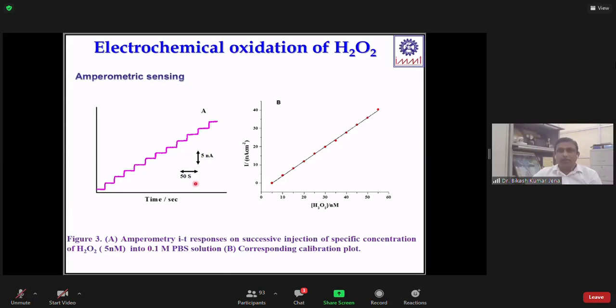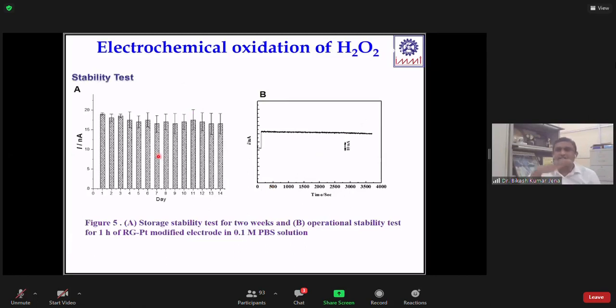When you put the hydrogen peroxide on the graphene and branch platinum nanoparticle modified electrode, what happens? Hydrogen peroxide gets oxidized and quickly gives the electrical signals, and those electrical signals can be measured through the increase in the current. We can see this one. So as this branch platinum nanoparticle modified graphene electrode is very good towards hydrogen peroxide, we thought that we can use it for development of some oxidase-based biosensor.